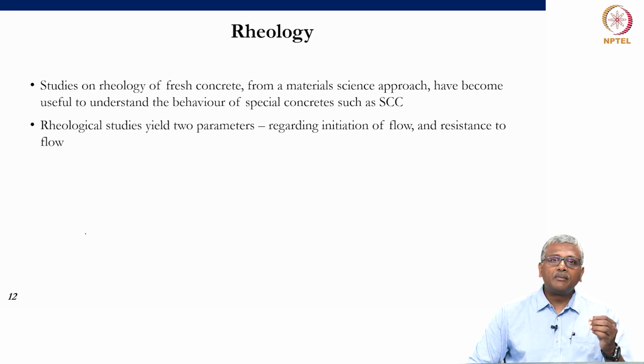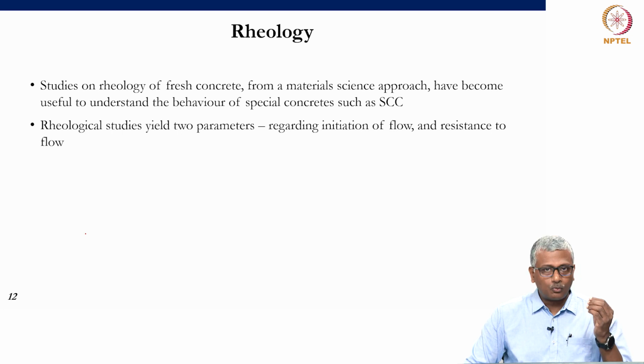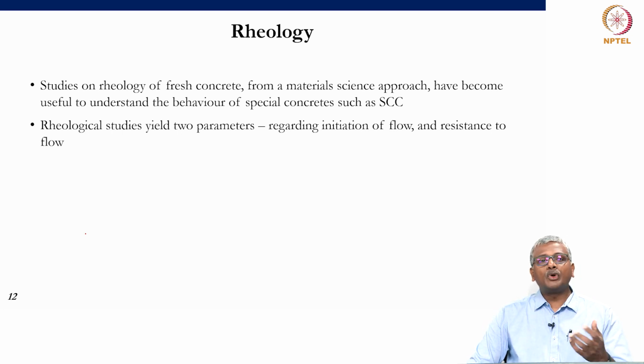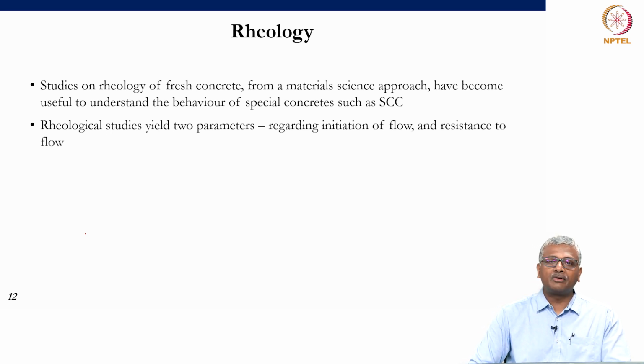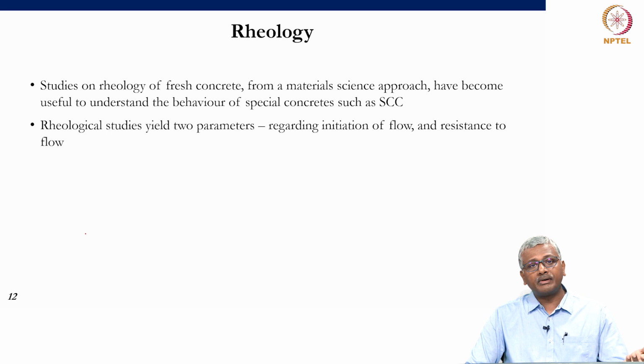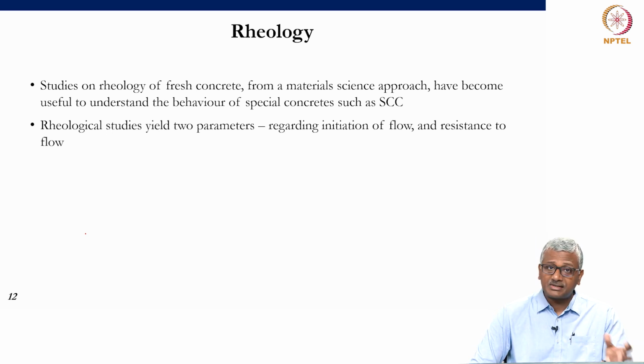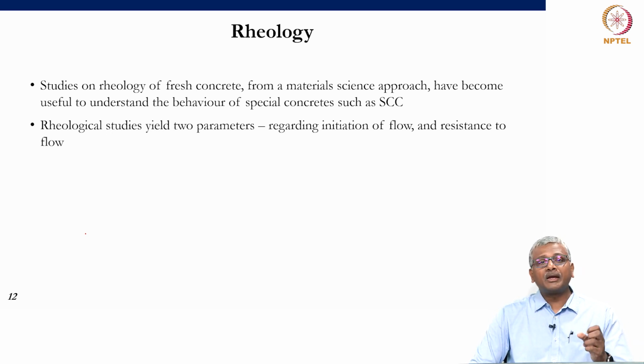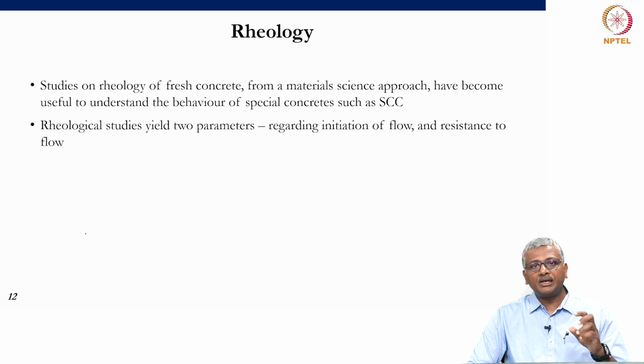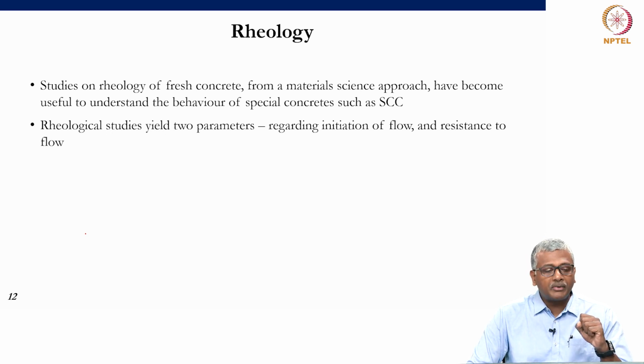As I said earlier, workability is too complicated to measure with just one property. So very often you have people going for a measure of rheology, which gives a lot more understanding about the flow behavior of concrete and other construction materials. So rheology, especially when it comes to flowing concretes like SCC or sometimes even very stiff or harsh concretes, can become quite useful to study. And in some instances, you can actually study these with simple test methods without the need for very complicated rheometer type approaches.